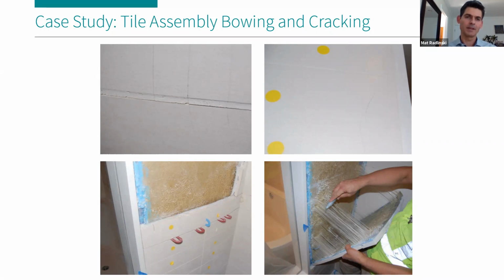And in many locations, the condition you see on the lower left was fairly common. It was an extreme amount of bowing of the entire tile assembly, accompanied by closely spaced craze cracks on the tile surface. And what we discovered in this case is that the relatively thick layer of the tile thin-set mortar, cementitious product, resulted in this bowing or curvature that was such a high level of stress that the underlying waterproofing membrane adhesive was unable to restrain or accommodate.